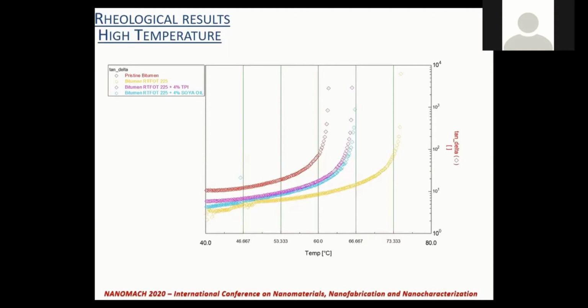At high temperatures the transition temperature is evidenced when tan delta is plotted against the temperature, up until the point where it's no longer visible on the plot. We observed that the transition temperature increased with the aging process. Both additives decrease the transition temperature of the bitumen, and they both have a similar rheological profile. However, with this analysis, we were unable to distinguish the rejuvenating effect from the fluxing effect.